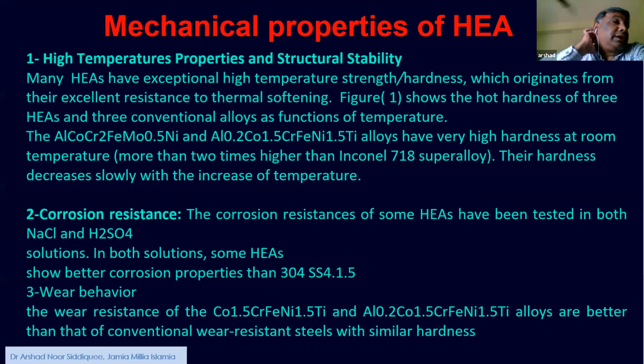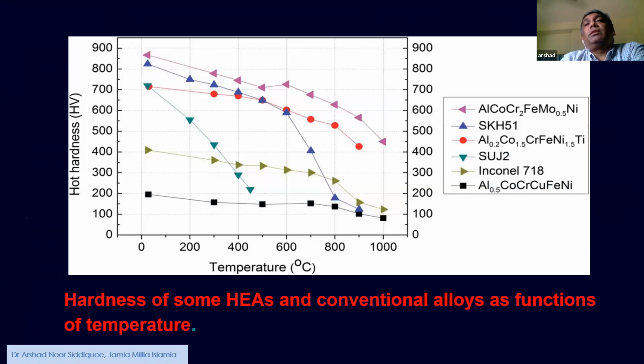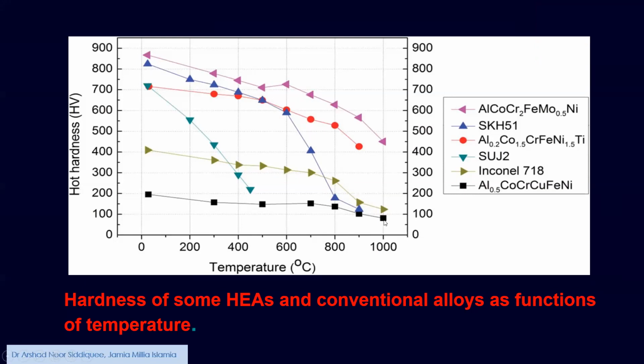Of course, as the temperature rises, the strength and other properties of traditional materials reduce very sharply, whereas in the case of high entropy alloys, the performance is steady. You can see these are all the different types of high entropy alloys with different colors of geometric shapes, and you can see the hot hardness at a temperature of 1000 degrees Celsius. The material was heated and its strength was measured in the hot state, and you will see that it usually maintains a steady hot strength. So this is one of the plots that depicts the relationship of hardness with temperature.